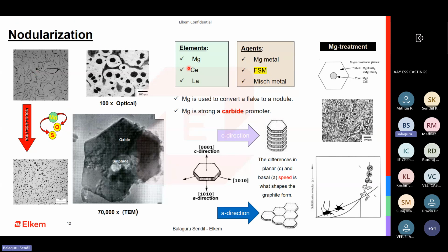The most important elements are magnesium, cerium, and lanthanum. The first ductile iron was experimentally made with cerium, but due to commercial viability, magnesium has been prioritized and commercialized to a far extent. How do I introduce these elements? I can either use very pure magnesium and plunge it, or I can go for ferrosilicon-based magnesium. I can go for a mischmetal type to have magnesium introduced for the process of nodularization.